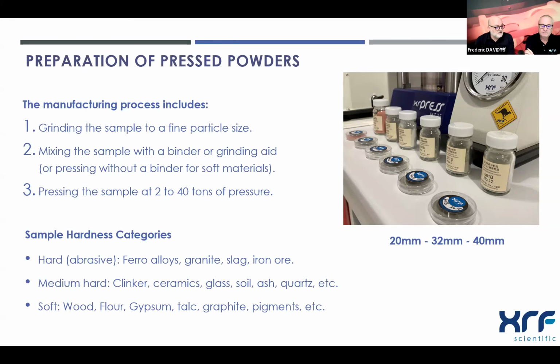So generally we prepare pressed powder pellets of 20, 32 or 40 millimeters. And when we speak about sample hardness, of course, the conditions will be different if we are dealing with ferroalloys, granite, or slags; iron ore is considered hard, whereas soft products like flour, wood, or gypsum can be pressed without any additives and are really easy to form.